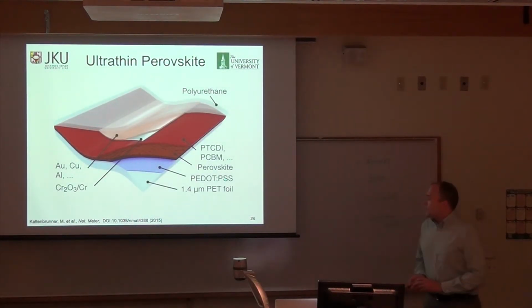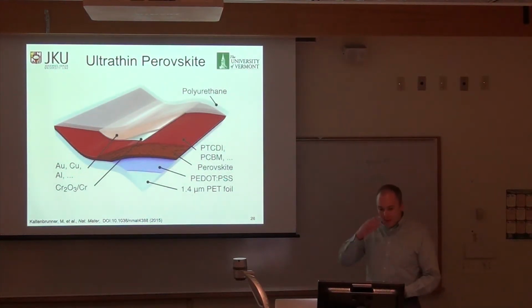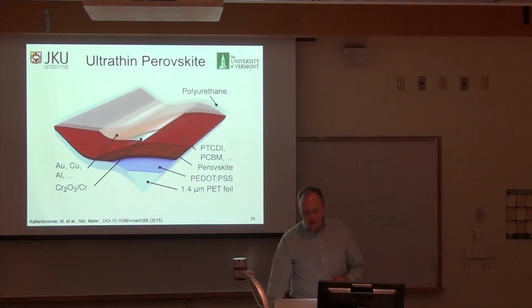The ideal structure that we want is our 1.4 micron thick foil, our transparent electrode, perovskite, our electron selective contact, and a back metal. Polyurethane encapsulant is optional - it doesn't provide much other than structural support.